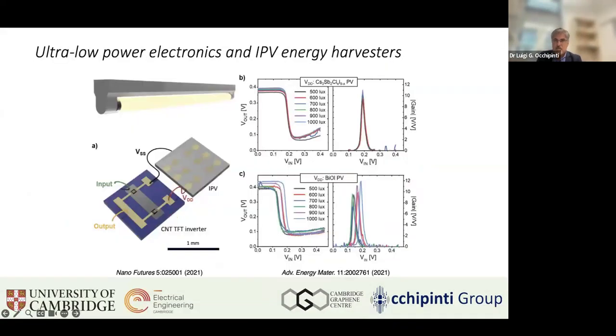And then, of course, we combine the two. As mentioned, using indoor photovoltaic lead-free perovskite, we can still harvest enough energy to run an ultra-low power electronic device without battery. Here, this was demonstrated with a millimeter size IPV cell powering a millimeter size printed carbon nanotubes TFT inverter. So the system was self-sustaining with energy coming from indoor lighting sources with between 500 and 1,000 lux in terms of luminance.